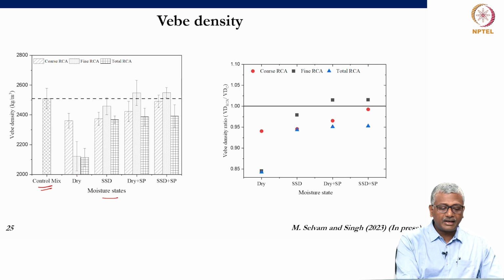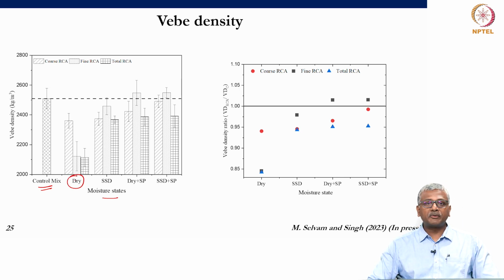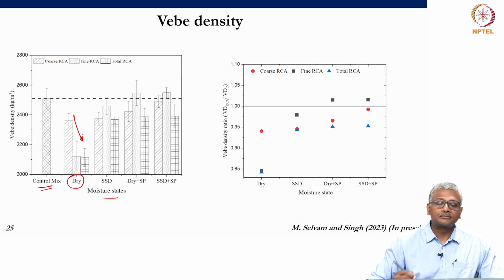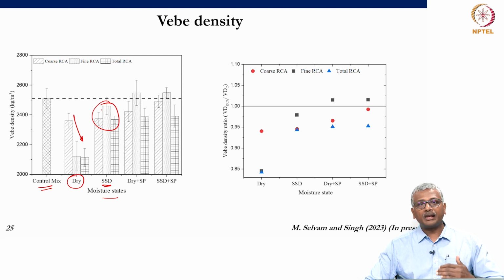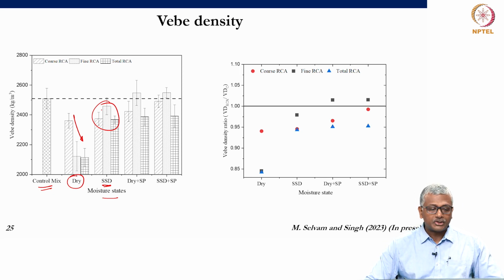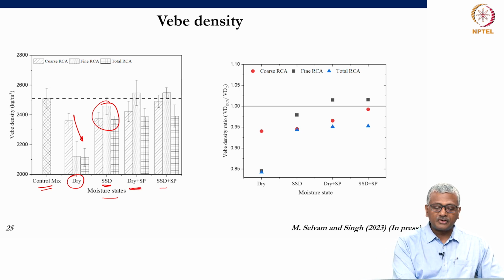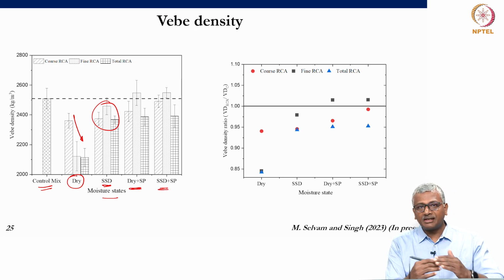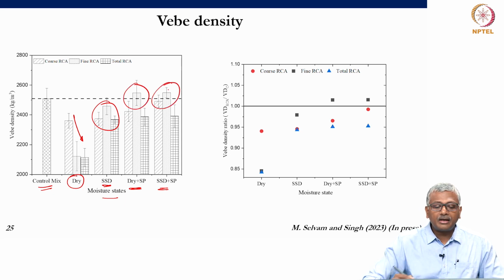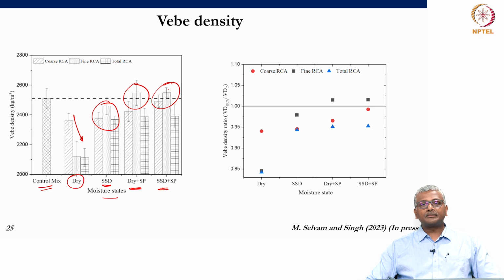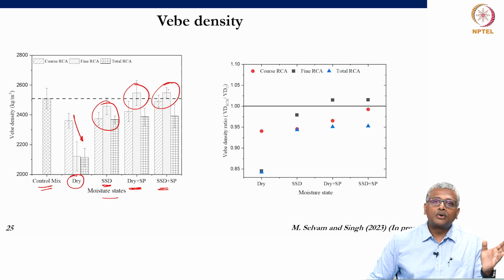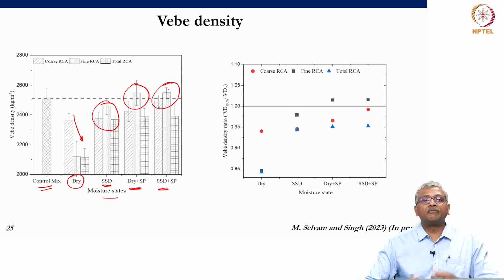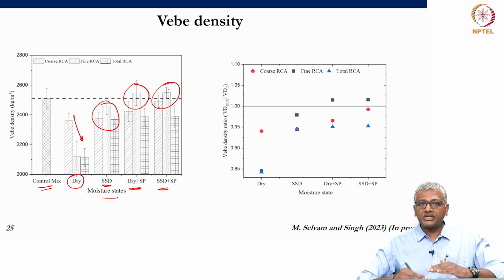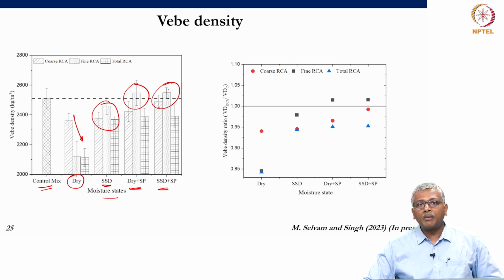When the moisture state of the aggregate was dry and the same concrete was prepared, the Vebe densities were then lowered. But when SSD was used, Vebe densities could be increased, but not to the level of the control concrete with normal aggregates or natural aggregates. When superplasticizers were used, the degree of compaction could be achieved significantly, so that the densities achieved were now closer to that achieved with normal aggregate. And this is very good, because now it tells me that I can now design roller compacted concrete pavements with optimal control of my superplasticizer dosage to produce compaction levels which are equivalent to my normal aggregate concrete.